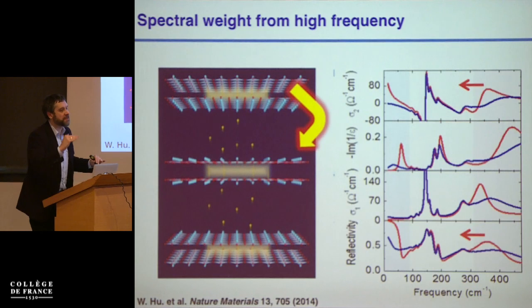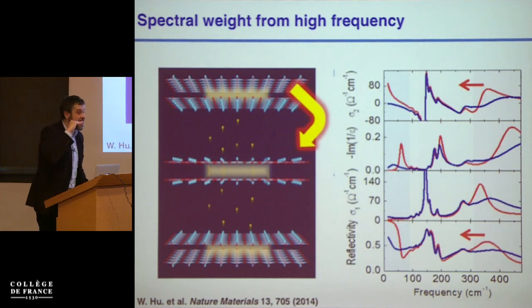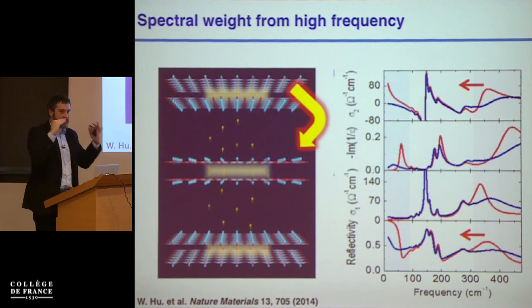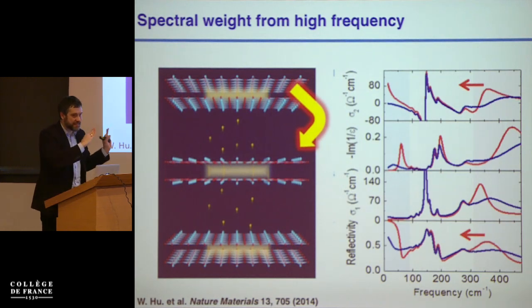Now, in-plane measurements are hard in cuprates because the equilibrium reflectivity is extremely high. So I can elaborate a lot why these measurements may not be reliable, the ones in the plane. You're measuring changes in reflectivity from something that already has a 99.9 static reflectivity, so it's very difficult to phase, and there's all sorts of reasons why this could be wrong. But we were not able to see any change in plane.